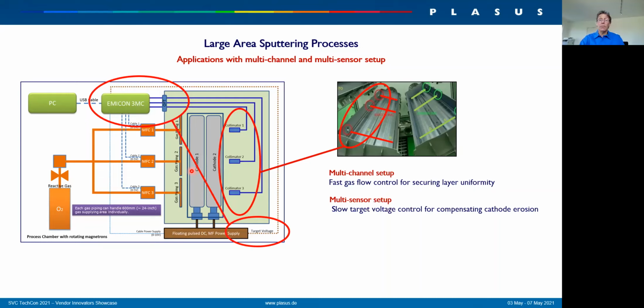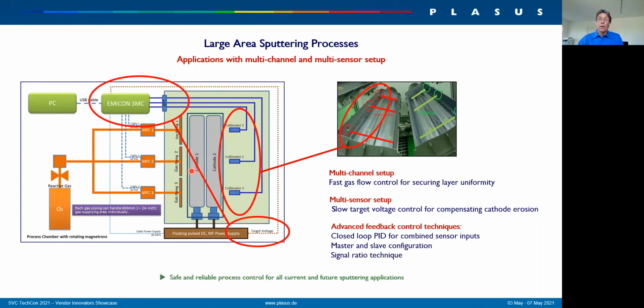And in addition, you can even monitor the target voltage, which gives you some information about the target erosion. With this information, you can easily recalibrate the set point of the gas flow control in the reactive process. So even in these rather more sophisticated applications, the Emicon system can provide a safe and very good control of the plasma process and thus of the production.